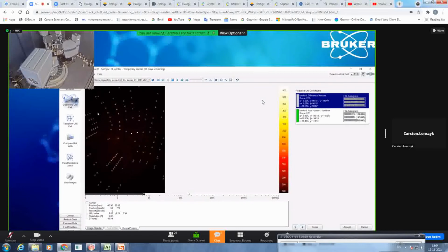And you see here that you have a nicely fitting unit cell found. So what does it tell you? This is the real space. This is the reciprocal space. And with a deviation of 0.1, it could already assign 95% of all reflections. So it's 422 of 442 reflections it could successfully assign to this unit cell it found. So this is very reasonable. So we accept this solution.